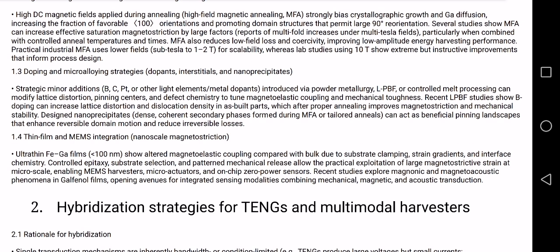Doping and microalloying strategies. Another exciting research direction is microalloying. Small additions such as boron, carbon, and platinum can modify lattice defects and improve domain motion. For example, boron doping in LPBF FeGa increases dislocation density after annealing, improves magnetostriction, and improves mechanical stability. Nanoprecipitates as controlled pinning centers improve reversible domain motion and reduce energy losses.